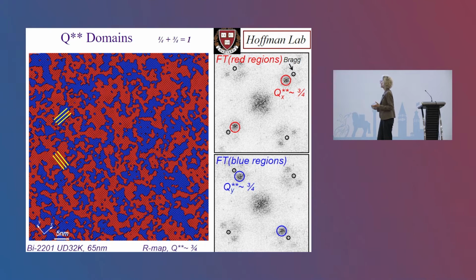And what Jenny's group has done is in a local region, they take a Fourier transform of the R map. The R map is where you take the current at one voltage and divide by the current at the negative voltage. So for example, this one is current at 100 millivolts divided by current at minus 100 millivolts. One advantage to that is that the matrix elements cancel out there. And so it's a nice way to highlight changes in local electronic structure. And so they take a local Fourier transform in any given region of space. They see structure. This is the Bragg peak of where the copper atoms sit.